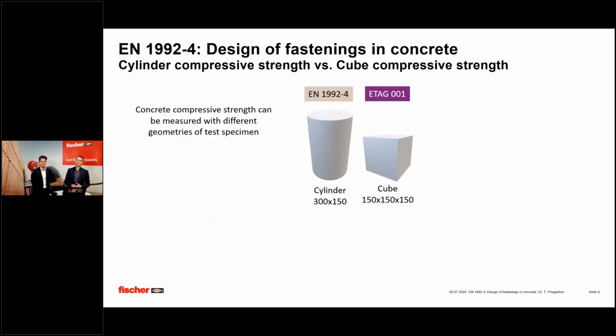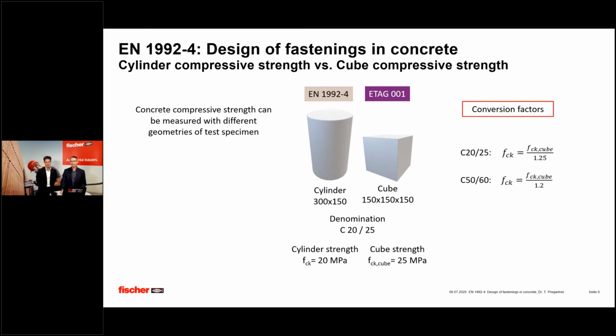Perfect. Then another topic which is pretty important and sometimes a bit strange if you look into the code in detail is that the reference of the compressive strength testing specimen changed. So in general, you have the possibility to measure concrete strength with 300 millimeter cylinders, as shown on the left, or 150 millimeter cubes. You see that already in the denomination of our concrete compressive strength classes. So we usually have two values that define a strength class. For example, C20/25 means a cylinder strength of 20 megapascal and a cube strength of 25 megapascal. In these values, as they characterize the same and the identical concrete, you see already that there is a conversion factor in between, which has the value of 1.25 in low strength concrete and 1.2 in high strength concrete.